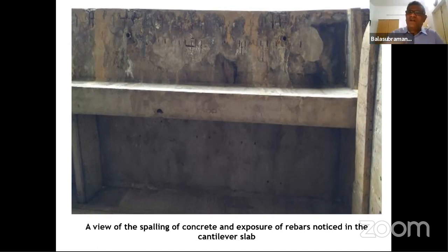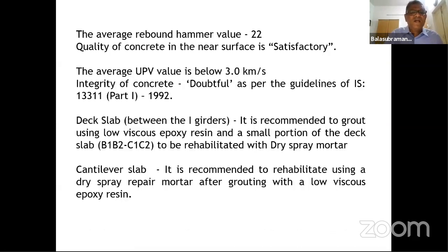It keeps accumulating. You will see so much corrosion, rebar corrosion, everything. You have to pay unnecessary money. Instead, if they had done the rainwater spout properly, gone there every 3 months, 4 months, and rectified it, all these problems would not come. And for the cantilever deck slab, we again recommended using dry spray mortar because microconcrete jacketing was just not on, because we had to cut a core through the deck slab where the traffic was moving.